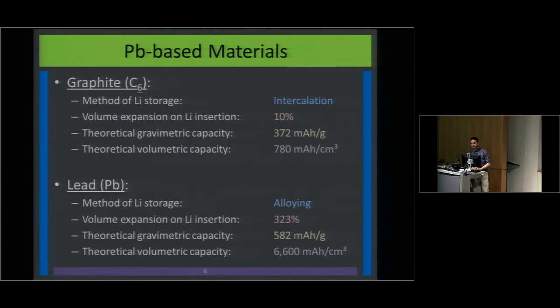So when that happens, you only experience about a 10% shift in volume. You can only store 1 lithium ion per about 6 carbon atoms, and this gives you a pretty low gravimetric capacity of about 372 milliamperes per gram. Also, graphite isn't very dense, so if you look at volumetric capacity, it's pretty low too.